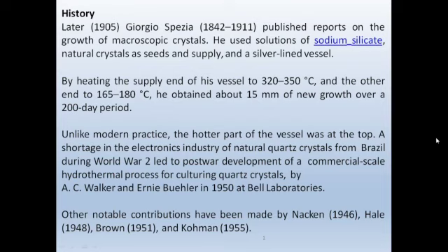By heating the supply end of his vessel to 320 to 350 degrees Celsius and the other end to 165 to 180 degrees Celsius, he obtained about 15 millimeters of new growth over a 200-day period. Unlike modern practice, the hotter part of the vessel was at the top.